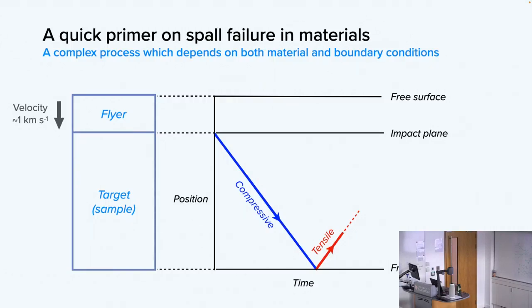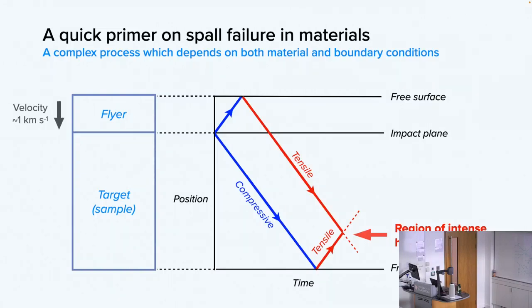Now, of course, exactly the same thing is happening in the flyer. So now there's a compressive wave in the flyer, which reflects off of the free surface at the back of the flyer as a tensile wave. That tensile wave is going to propagate into my target, and it's ultimately going to overlap with the tensile wave that's reflecting off the back surface of the target. And where those two tensile waves meet, I can have extremely large hydrostatic tensile stresses.